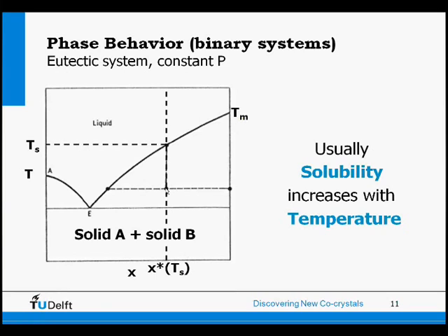And well, you want to know the solubility of these crystals, so if you then slowly heat them up and record the temperature, and then there will be a temperature where the solution becomes a clear solution, and that is the saturation temperature if you measure accurately enough. And this saturation temperature, you know the composition of that saturation temperature, so you know a solubility point in your solubility graph. So here you see that usually solubility increases with temperature.